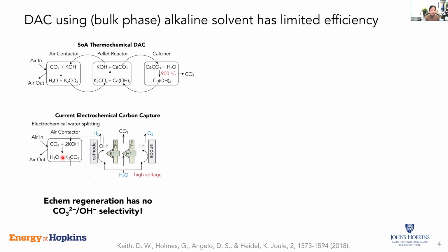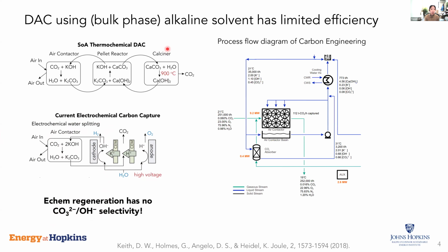So that really gives us a challenge, because the bulk phase alkaline solvent in our state-of-the-art air contactor is really not very efficient. Because of the really dilute CO2 concentration in the air, the hydroxide utilization efficiency is roughly 10%. Meaning that if we send 10 hydroxide ions into our air contactor, only one of them gets to react with carbon dioxide, and the rest of them will remain as hydroxide. And that would really limit the electrochemical efficiency when it comes to regeneration.